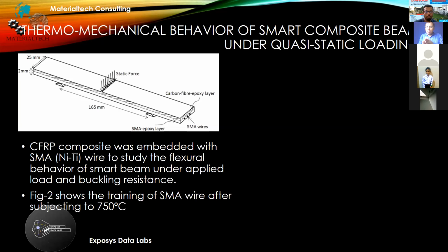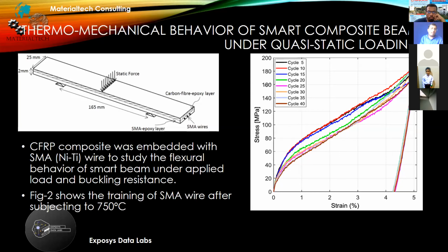We investigated how it behaves, how it sustains the stiffness of that particular composite, how it benefits under the 3-point bending, and how it can retract back under the influence of mechanical forces and crack propagations. So that's what we have done. As I told you earlier, we subjected this to 750 degrees Celsius to train it to the original level, that is, to make it understand the original crystal structure. And then we trained it at different cycles.